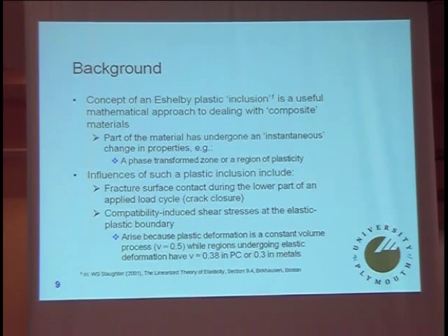So if you look at the mathematics, some time ago, Eshelby, who was really quite a decent mathematician and dislocation specialist, proposed the concept of plastic inclusion as a mathematical approach to dealing with composite materials. Now in this context, composite means part of the material has undergone instantaneous change in properties. So what he was talking about was either a phase transform zone or a region of plasticity. Now it turns out the mathematics of dealing with Eshelby inclusions is not straightforward, but is possibly or probably feasible.